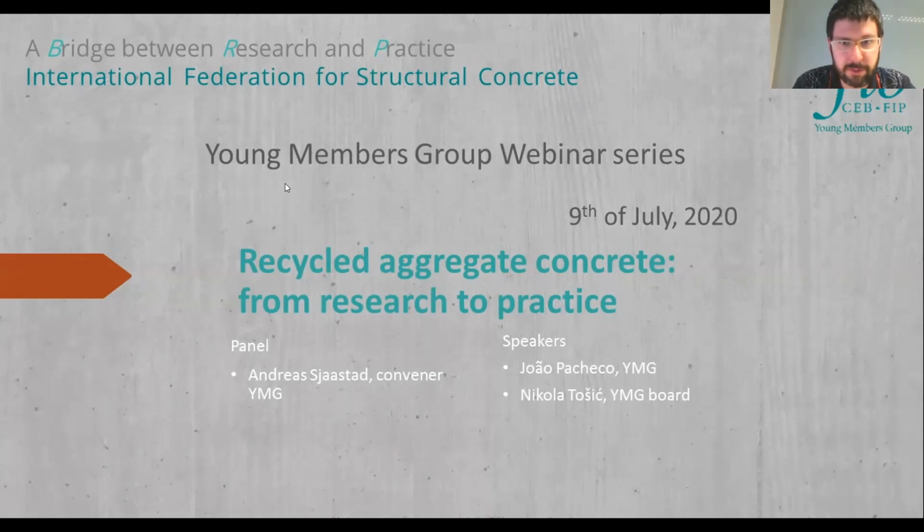Okay, crushing value, yeah. Well, you're surely going to be able to draw a correlation between the crushing value and the effect on compressive strength, but honestly not in some really generalizable way, so that you can extrapolate just from this to make it a predictor of compressive strength. Not really, but once knowing your aggregate, like you have your batch of aggregates from the plant, doing a few trial mixes and drawing correlations from there is going to help you a lot to do other calibrated predictions. So I think it will have a large correlation with the compressive strength, but locally.